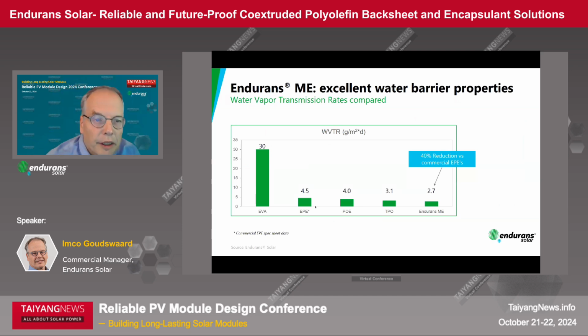Here's some data. This is with respect to the water vapor transmission rate. On the left side, you see a relatively high rate for EVA, and then significantly lower for EPE and POE, which are close together. And then by changing the POE core layer, we get a further 40% reduction of the water vapor transmission rate. Like I said, which also will have an effect on acid formation. Next slide.